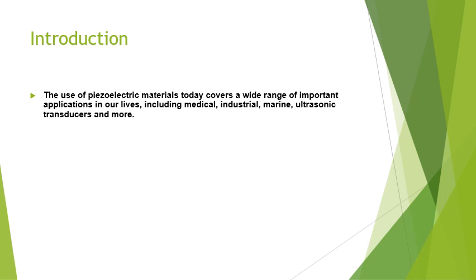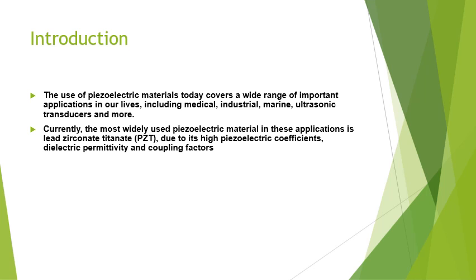So, to this day, the integrated piezoelectric occupies all the aspects of our modern life, which is a common phenomenon of mechanical energy converted to electrical energy and vice versa. So the use of piezoelectric material today covers a range of important applications in our life, including medical, industrial, and ultrasound, especially ultrasound transducer. Currently, the most used piezoelectric material in the application is lead zirconate titanate due to high piezoelectric coefficient and dielectric permittivity, also the coupling factor.